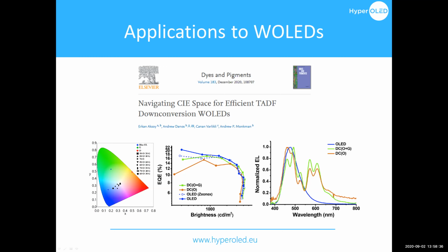It's quite hard to compare these directly because once you test an LED, you've usually destroyed it as well. So we couldn't go back and apply this process to the same LED and compare exactly with and without. But across the set of devices that we made for this, it looked like there wasn't really a substantial drop in efficiency compared to the blue LED underneath and the white LED that we constructed with the down converter layer on top.